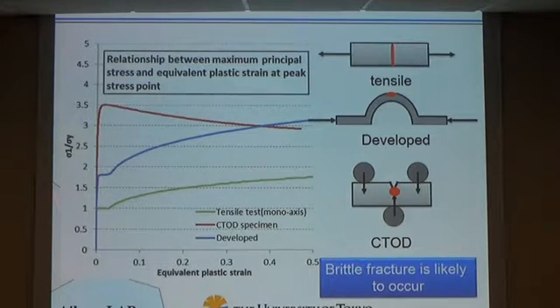And this figure shows a relationship between maximum principal stress and equivalent plastic strain at the peak stress point. The original tensile test shows very high equivalent plastic strain, so brittle fracture doesn't occur in this test. On the other hand, the CTOD or three-point bending test shows very high principal stress before plastic strain. And so brittle fracture is easy to occur, but we can't observe the trigger point of brittle fracture directly and in situ because the trigger point is at the front area of this notch, so we can't observe there. On the other hand, this specially designed specimen shows the balance between principal stress and equivalent plastic strain, and the maximum principal stress area is the top surface area, so we can observe the trigger point of brittle fracture very easily.